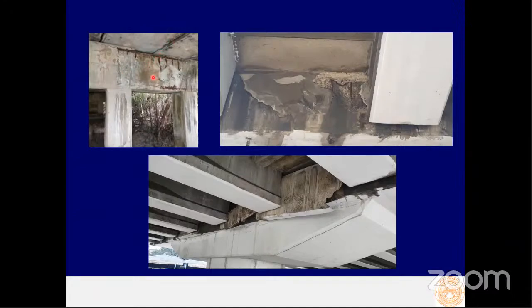That micro crack can allow water to penetrate into the concrete very easily. And if we have no corrosion protection, it causes corrosion to the substructures. It can form corrosion damage like in these pictures. Another type of damage due to corrosion in the land bridge is the overpass damage due to corrosion